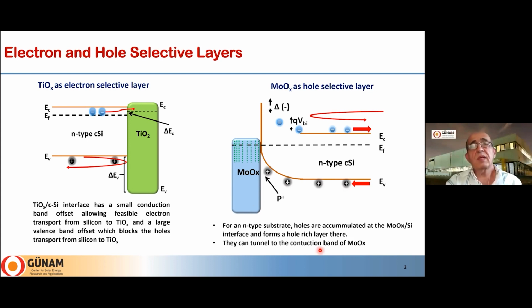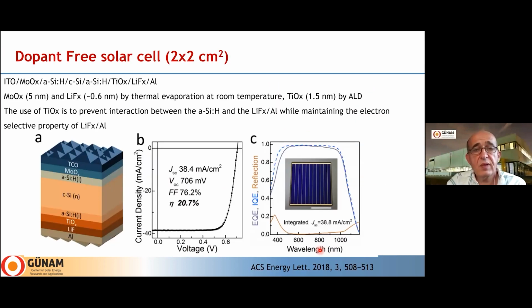There have been several studies recently. One of them is a very recent work published in ACS Energy Letters. Here they use molybdenum oxide on one side and titanium oxide on the other side. But still they used amorphous silicon for passivation purposes. These amorphous silicon layers are not doped, but you need them for the passivation, and the structure is shown here. On one side you have molybdenum oxide, on the other side you have lithium fluoride, and the efficiency they have reached is about 20%, as you see.